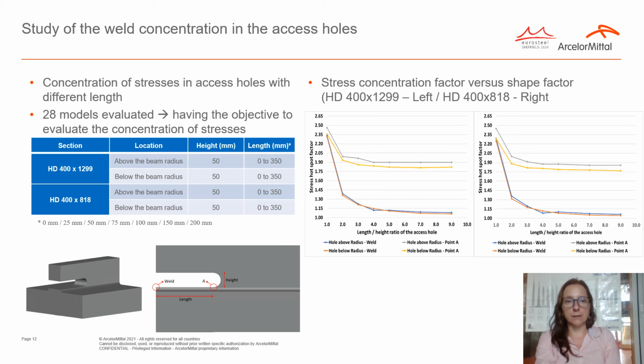And as a last point, a study of the stress concentration in the access hole having different geometry has been made. The main objective of the study was to evaluate the concentration of the stresses in the access hole having different lengths, and a set of 2 sections, and in total 28 models were evaluated, and the length versus the position of the access hole varied. According to the previous results, it was possible to conclude that the stress factor at the access hole area does not present significant variations with the size of the section and tends to stabilize around 100 mm length of the cut section.